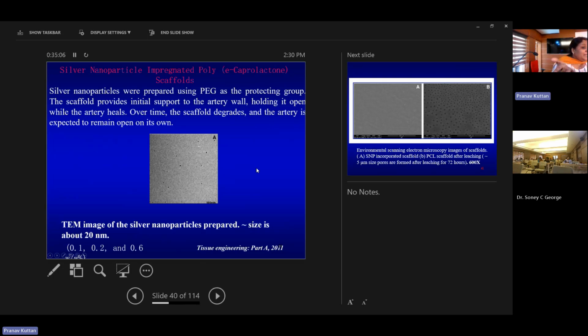So PEG is chosen because polyethylene glycol is highly biocompatible. And there is one more reason that I will explain. We develop the silver nanoparticle protected with polyethylene glycol, and the vascular scaffold will be developed using polycaprolactone. Polycaprolactone, as you will know, is a stable synthetic polymer which degrades slowly. It doesn't degrade very fast. So when you incorporate this PEG-containing silver nanoparticle inside the polycaprolactone and put it inside the body or in a medium, the polyethylene glycol, being hydrophilic, dissolves in water. Since the medium is water, this PEG will slowly dissolve into the medium, and along with the PEG, the silver nanoparticle will also give antibacterial activity to the surrounding medium.